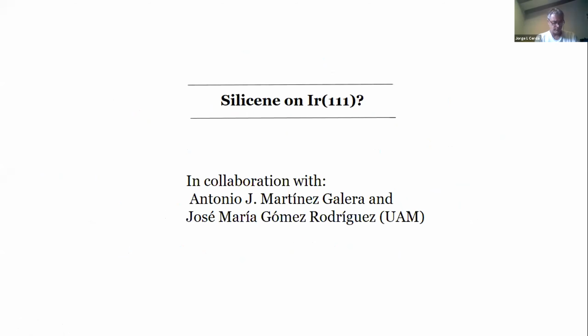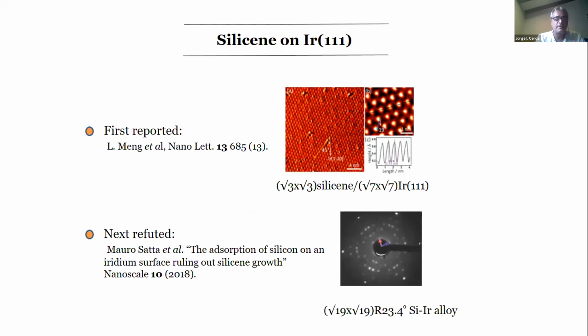If I have some more time, which I think I do, I would like to briefly mention silicene on iridium. This is in collaboration with people at Autónoma, with Antonio Martínez Galera and José María Gómez Rodríguez. As I said at the beginning, growth of silicene on iridium was first reported by this group in 2013. No one has been able to reproduce this structure, square root 3 times square root 3 and square root 7 times square root 7. A few years later, there was a group that actually refuted this structure. They said there was no way to obtain it. It was a core level study with a couple of LEED and DFT calculations. Basically, they were able to obtain an ordered structure, but they claimed there was an alloy of silicon and iridium. Before you obtain this structure, which would be at a high coverage of iridium, they claimed there would be some non-well-ordered structures with basically silicon atoms sitting at three-fold sites.